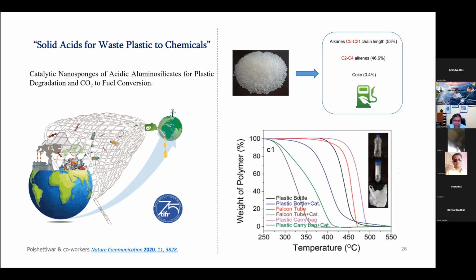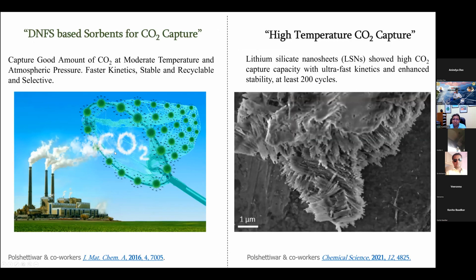I showed you one example, but we try to do a range of catalysis using this solid acid material. We also developed a CO2 sorbent in our lab, where you can either capture CO2 at lower temperature after it comes from industry, or capture CO2 at high temperature while it is produced in the reactor. You don't need to wait for the CO2 to come into the environment and pollute—capture it as soon as it is produced. So both processes we have recently developed.